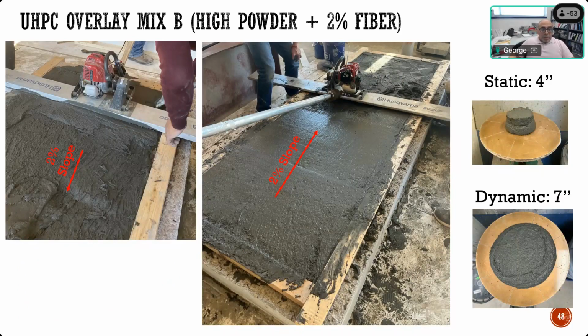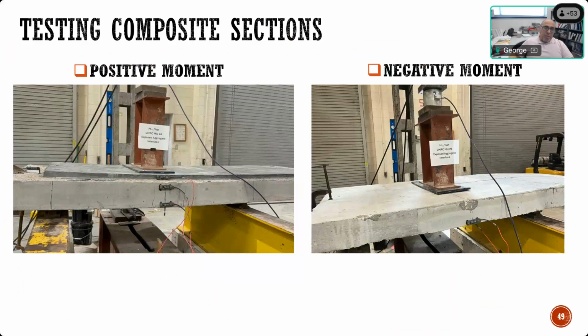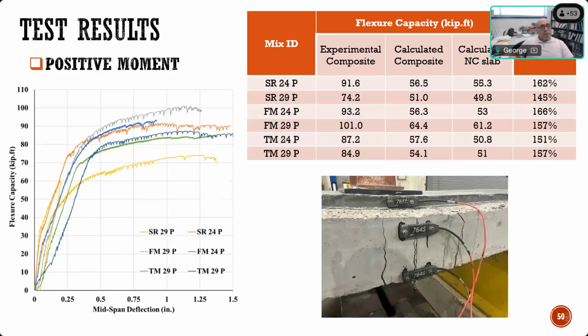So we did that experiment, and we also tested them cast on top of a conventional concrete deck. We tested in flexure, and then we flipped the specimen to keep the UHPC at the bottom, so we see the negative moment zone in the bridge deck and how it performed. So we evaluate the capacity in positive moment and negative moment. And we did that for multiple specimens with different types of surface preparation, whether it's a surface retarder, fine milling, or typical milling. And we looked at load deflection, or capacity deflection diagrams.